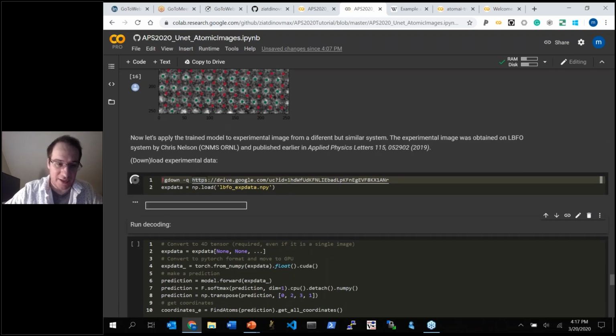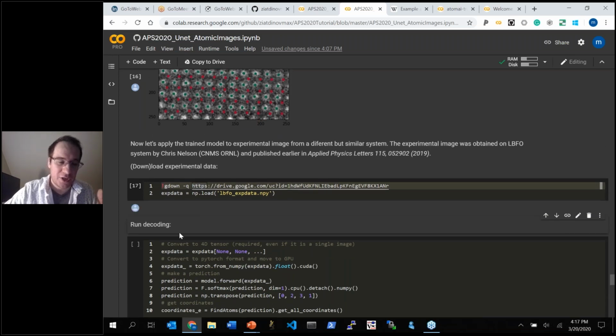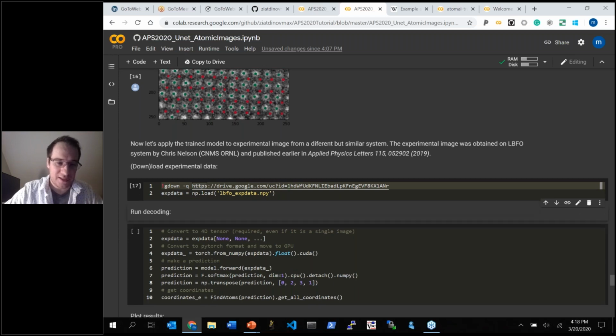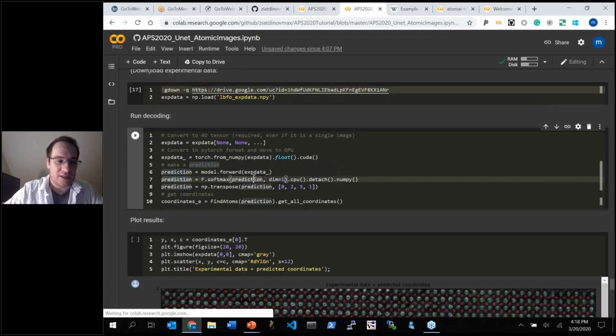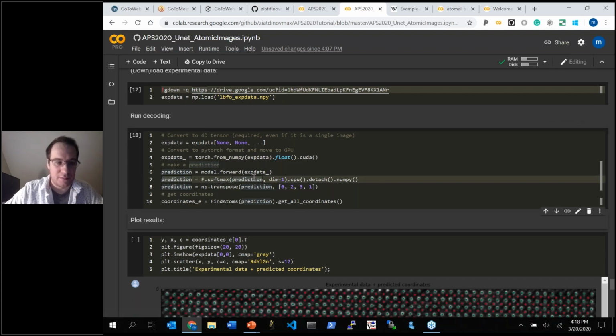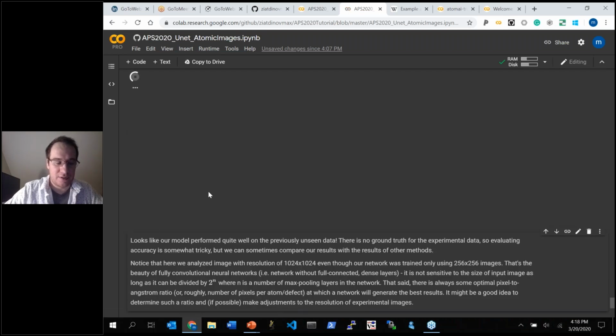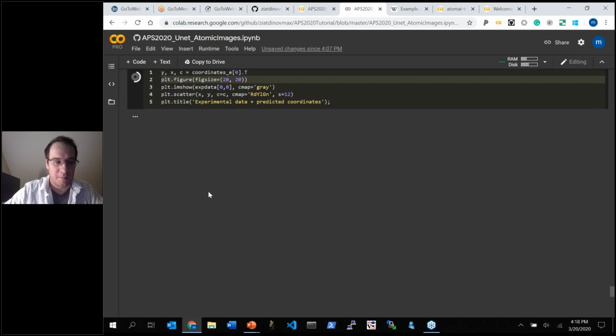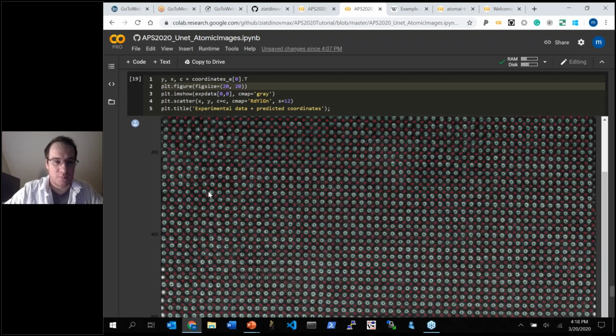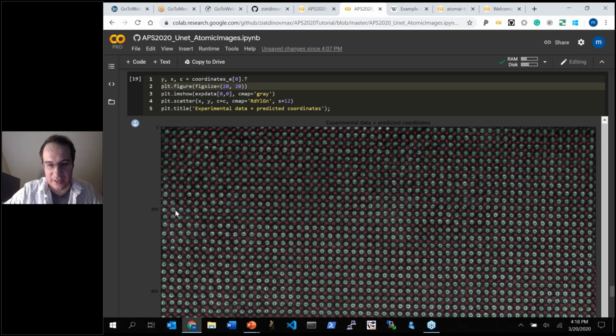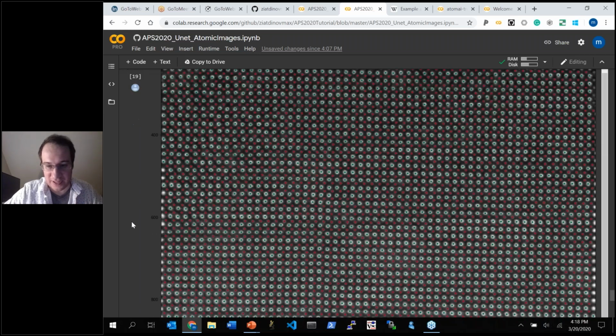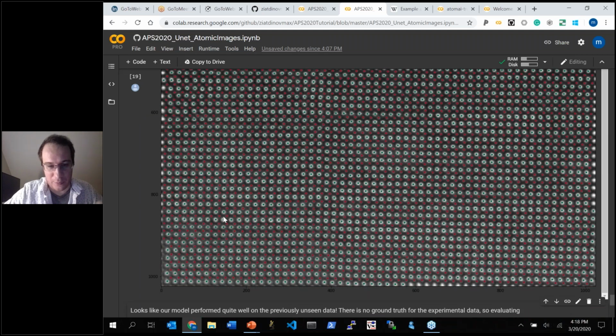Okay, and let me show you something. We can use this model that was trained on a single experimental image, and apply it to an experimental image from a slightly different sample. The host material is the same, but the experiment was different, and the dopants were different. So let's just apply the neural network to that image. It will take some time to plot. Okay, and you can see that when we apply it to a different image, it was able to find atoms in that different experimental image that the network has never seen before. And we have analyzed this image before, so I know that this is quite an accurate result.